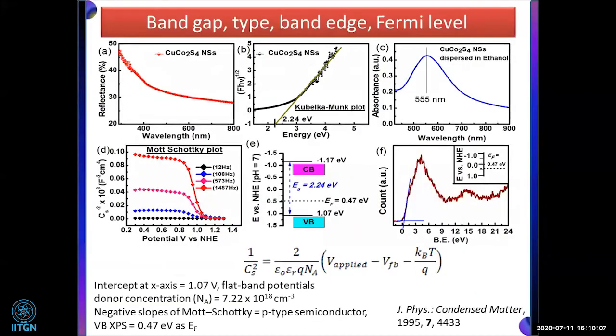If we see the first one, this is the optical study from the Kubelka-Munk plot. For the first time we established the band gap of this copper cobalt sulfide as 2.24 electron volt, a very good band gap for water splitting, if the CB and VB lie above and below the required hydrogen and oxygen evolution reaction potentials.